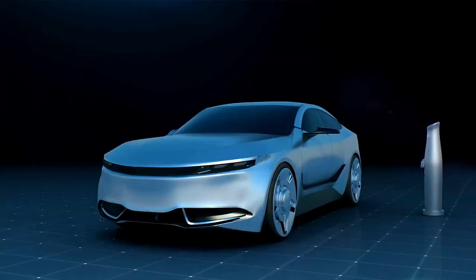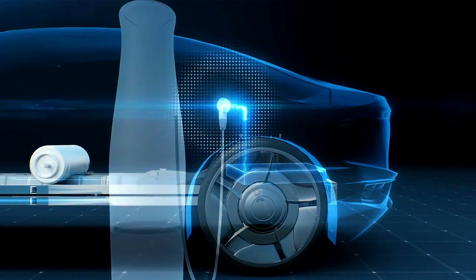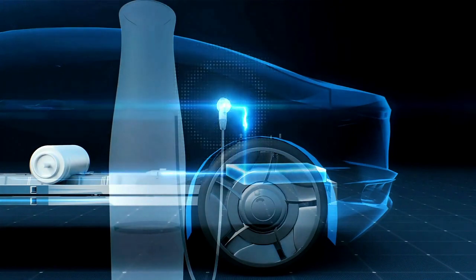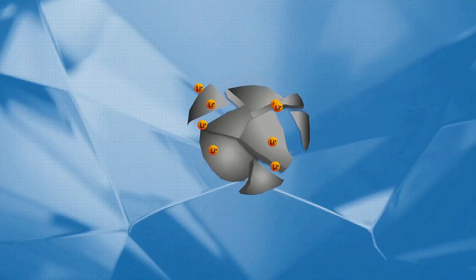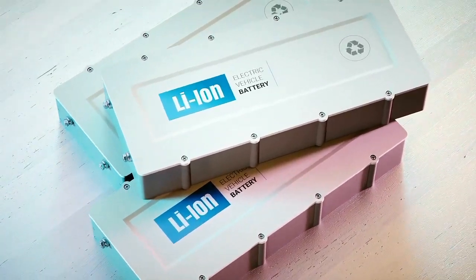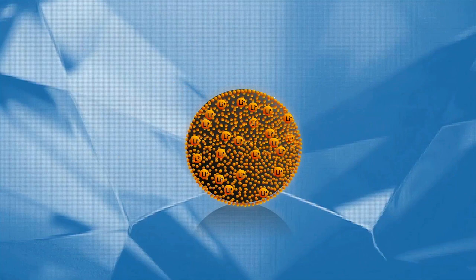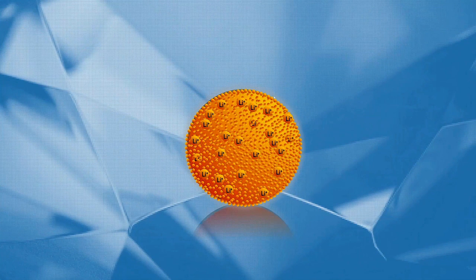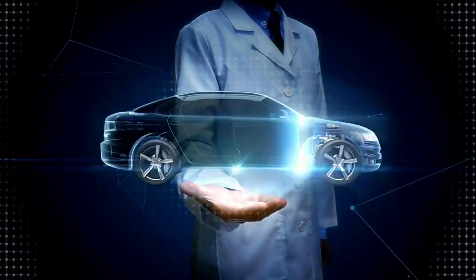However, metallurgical silicon is unable to be used in commercial lithium-ion batteries today due to two major technological barriers. Silicon expands up to 300% in volume during battery operation, causing swelling, fracturing, and battery failure. The second challenge is that silicon deactivates up to 50% of the lithium ions in a battery — called first cycle loss — where lithium ions are rendered inactive by the silicon, immediately reducing battery performance and life.